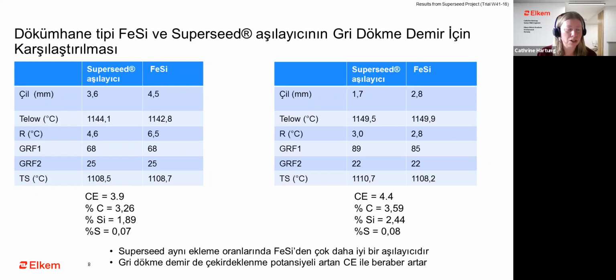And as we have then, we show the different parameters which we typically associate with nucleation and inoculation, which is chill. And then we have the most common thermal analysis parameters used. We have the Telow, we have the recalescence, the graphite factor 1, which is the length of the curve. I believe in the Elkem thermal analysis system, this is the equivalent to the LET to the, is it ST? And the graphite factor 2 is the angle at the end of the solidification curve. Then we have the solidus temperature. And then we can see the example here with Superseed versus foundry grade ferrosilicon at the low carbon equivalent.